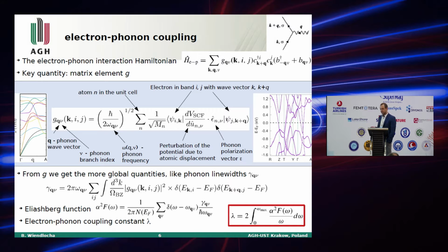So generally, here is the electron-phonon coupling interaction Hamiltonian, and the strength of interaction depends on this matrix element G, which to calculate we need a full knowledge about the electronic spectrum, about the phononic spectrum, and we have to deal with coupling of those two systems through these matrix elements. And if we have all this computed, we can calculate the strength of electron-phonon interaction, and from this matrix element we can get the more global quantities like the phonon line widths, and they enter the definition of the so-called Eliashberg electron-phonon coupling function, which depends on the phonon frequency. And from this Eliashberg function we arrive at the most important parameter for today's talk, the electron-phonon coupling constant lambda, which is an integration of this Eliashberg function.